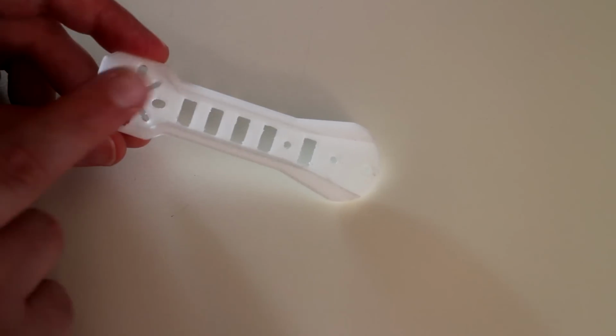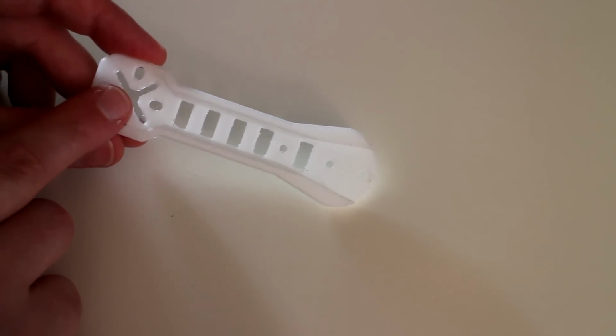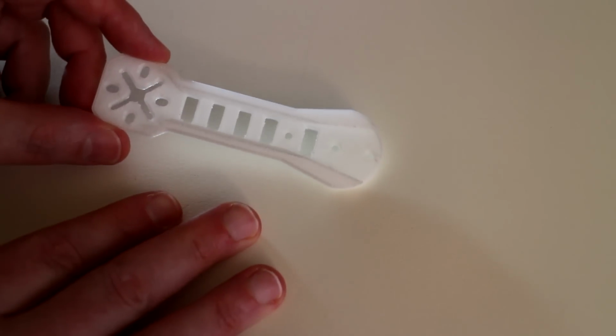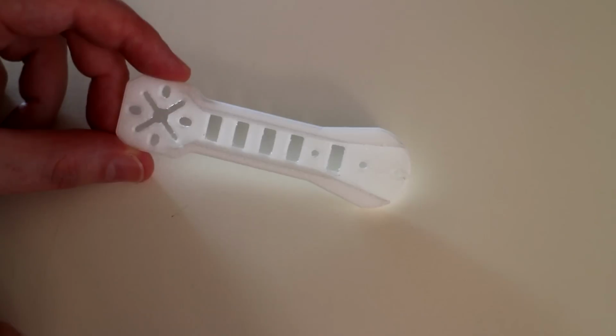I printed this at 245 degrees Celsius. The bed was set to 45 degrees Celsius, and no fans were blowing on this part while it was printing.